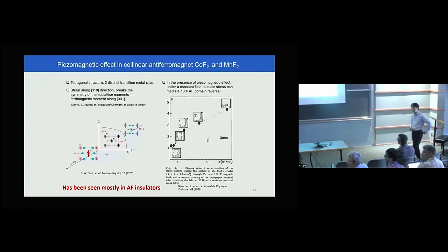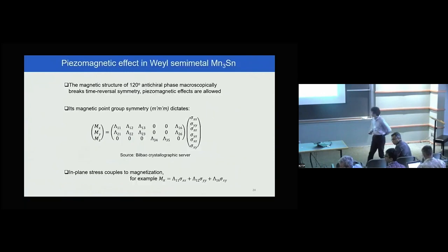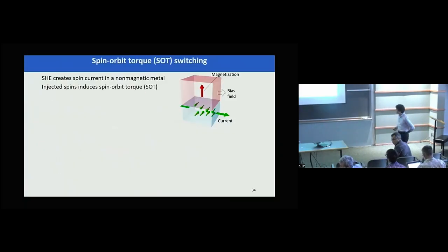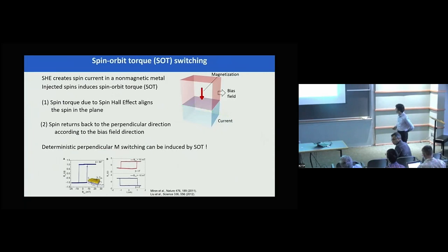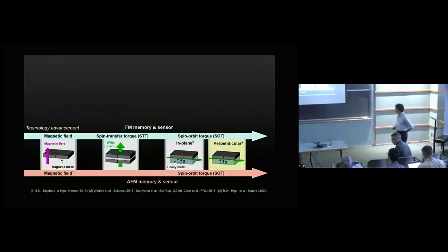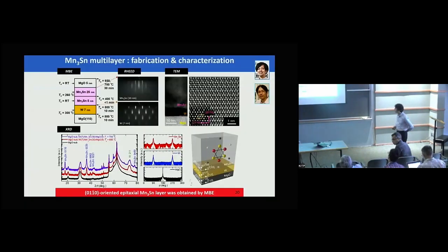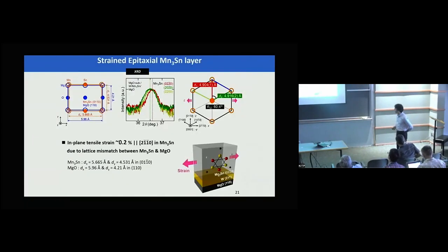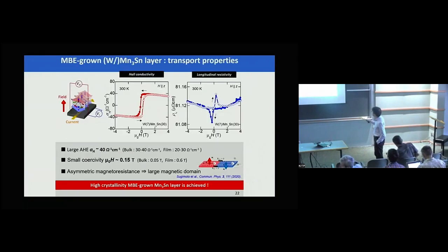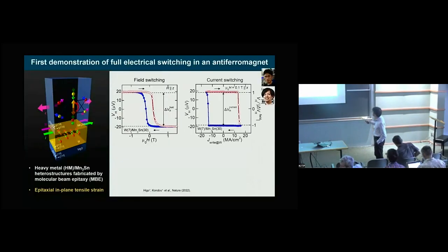So in your geometry of switching using spin orbit torque, when the magnetization switches in the Kagome plane, does the octupolar order switch out of the Kagome plane or inside the plane? So you were saying that the antiferromagnetic part, does this rotate inside the Kagome plane or switch by going out of the Kagome plane?